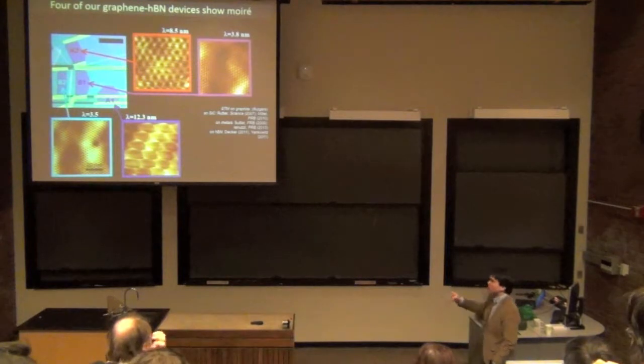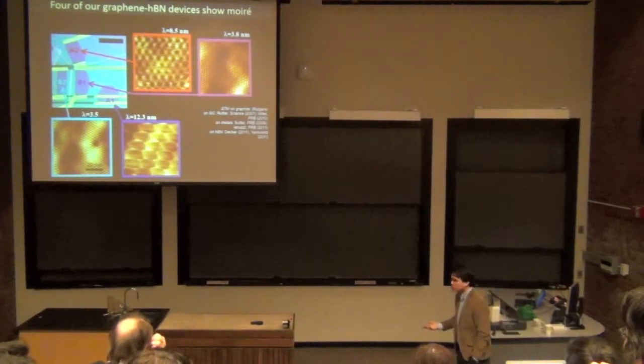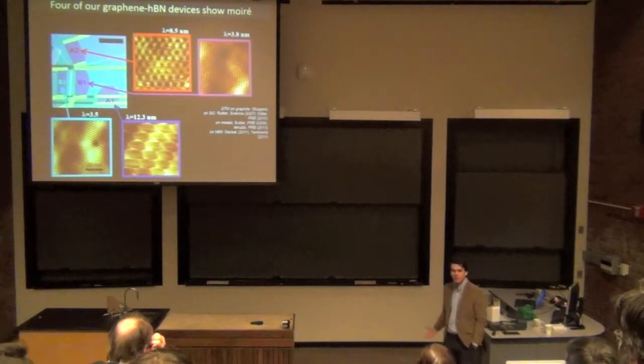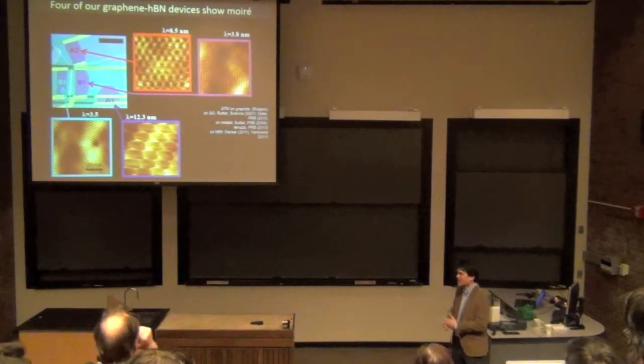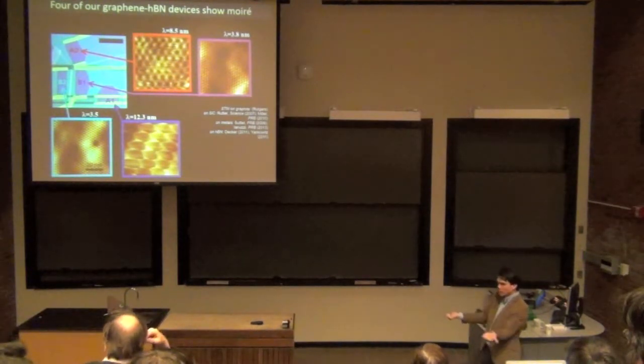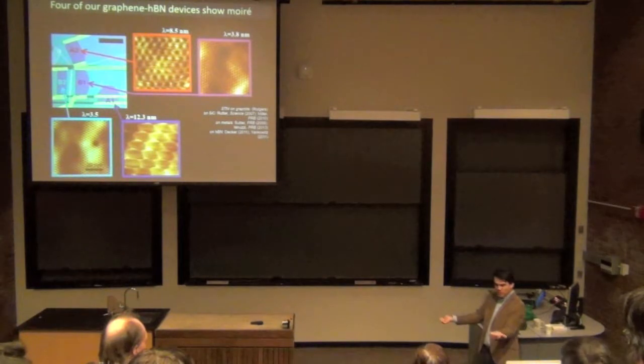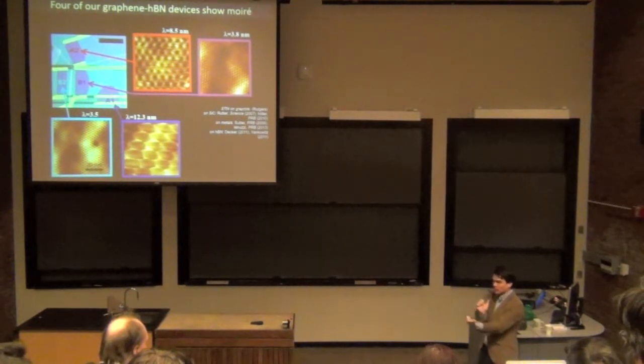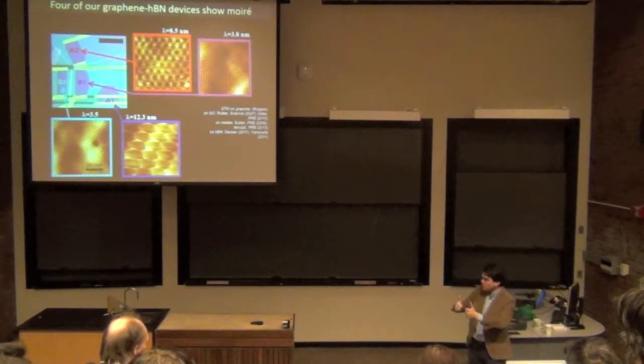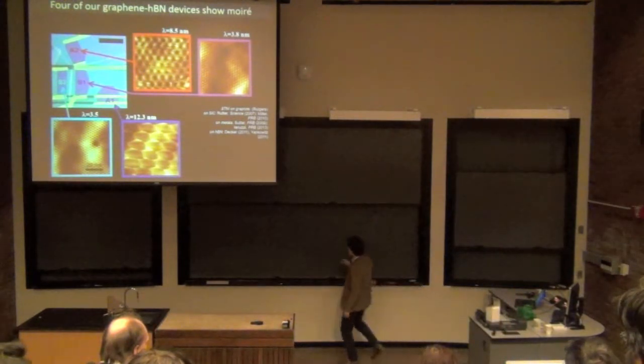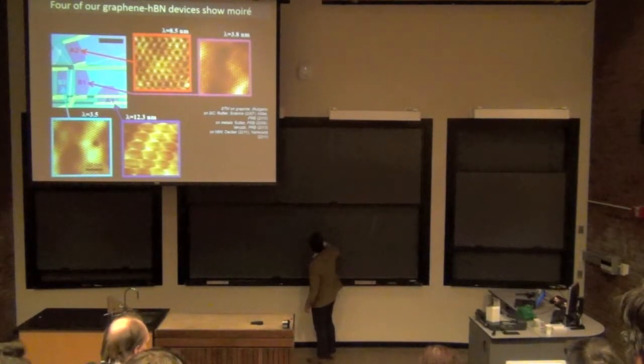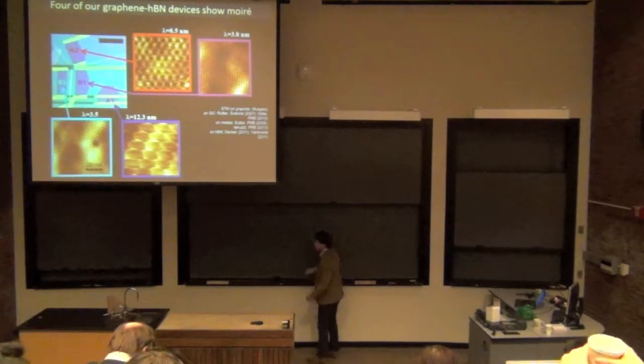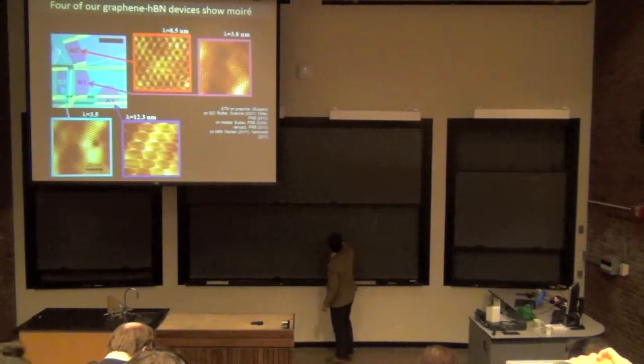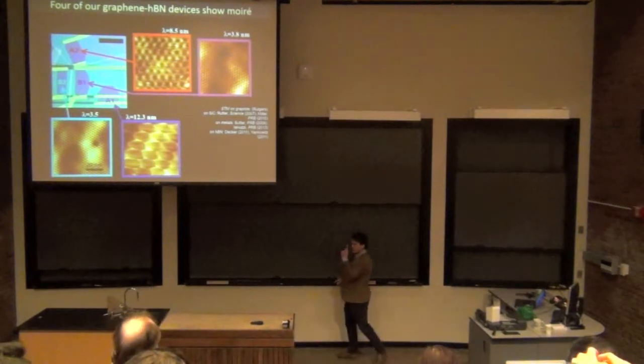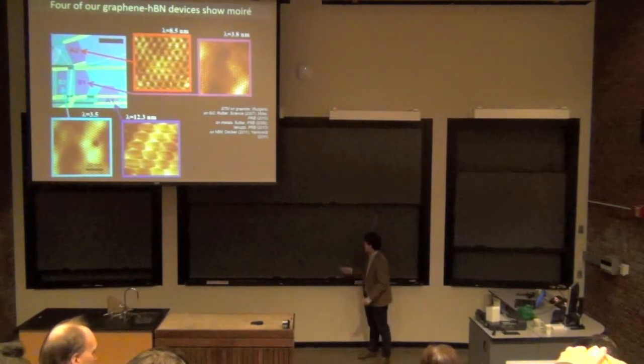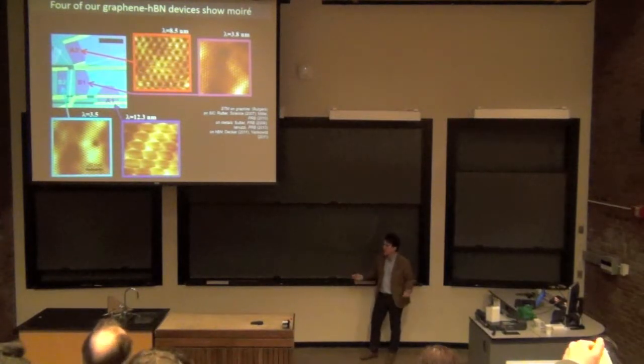I know it's probably on some people's minds. The analog of that symmetry in our system: our system is obviously not time reversal symmetric because it's working at 35 Tesla. But if you look at the alignment of the bulk spins, we go from a state in which we do not have rotational spin symmetry in the plane, the canted antiferromagnetic state, where the spins are like this in the bulk, we do not have the spin symmetry about this axis, right? But in the ferromagnetic state, we do have spin symmetry about rotations about the total magnetic field, and it's basically that symmetry that protects against backscatter in our system.